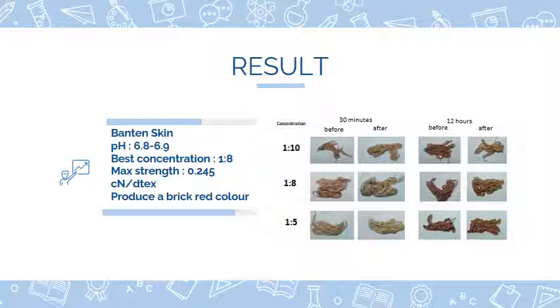The brick red color of the yarn is produced by dyeing it with the skin of the bantan tree. This brick red color appears because the skin of the bantan contains anthocyanin. Rose baby color for 30 minutes of immersion on the yarn was produced at all concentrations of the solution before fixation. However, after the fixation process, the rose baby colors start to fade.